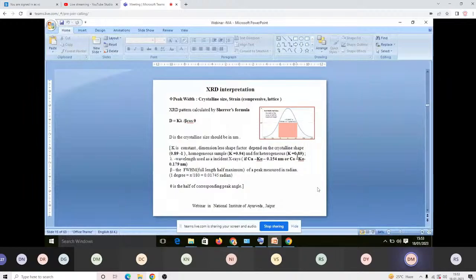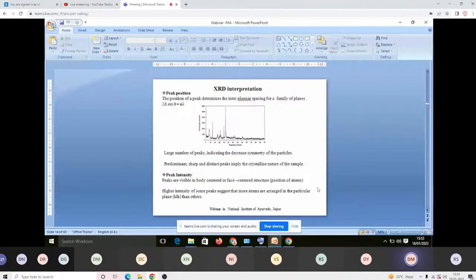Lambda is the X-ray wavelength, which is 0.154 nanometer. Beta is the full width at half maximum of the peak, in radian units. Theta is half the corresponding peak angle, which you previously see as 2 theta, so just take half of it. In that way you can measure the crystalline size.